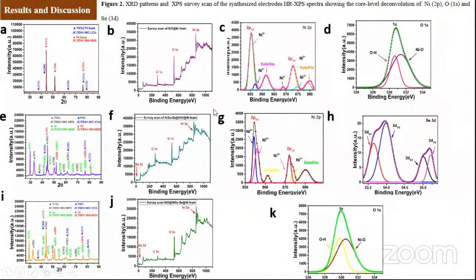Now, coming to the results and discussion part, figures A, E, and I show the XRD analysis of pure nickel oxide grown over nickel foam, and nickel selenide and nickel oxide grown over the nickel foam current collector. Figures B, F, and J show the survey scan of the pure and the composite electrodes which have been synthesized. Figures C and D show the XPS analysis, which shows the presence of nickel in different oxidation states. And similarly for the composite samples also, we have seen the presence of nickel in different oxidation states and selenium in different oxidation states again, accounting to selenium 2 minus and selenium 0.